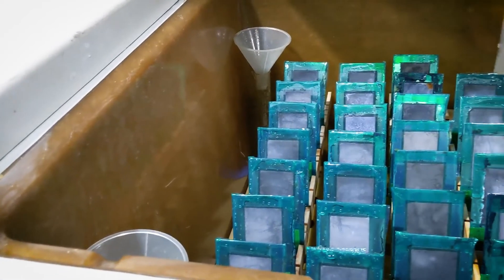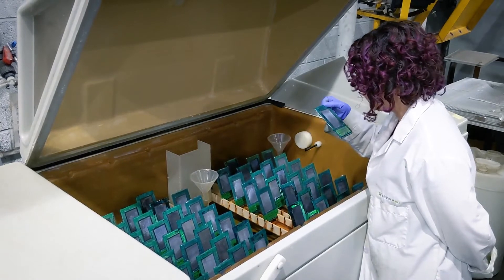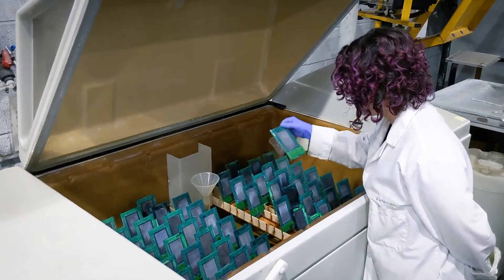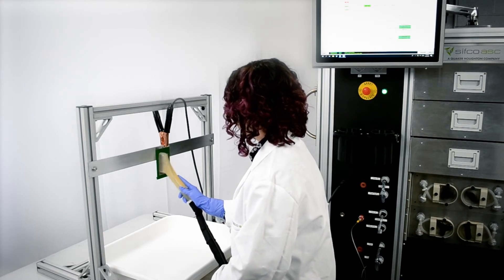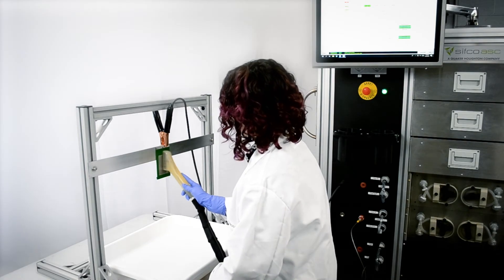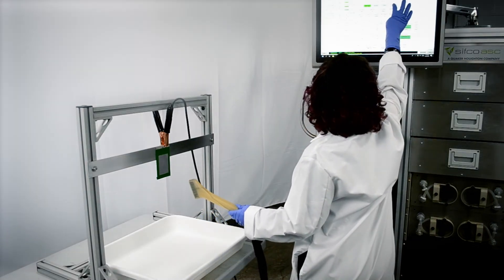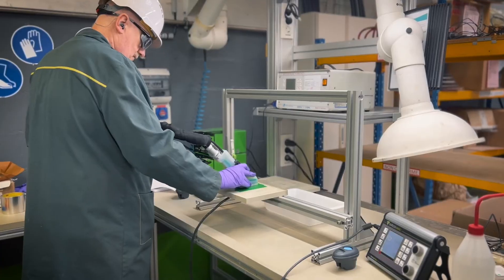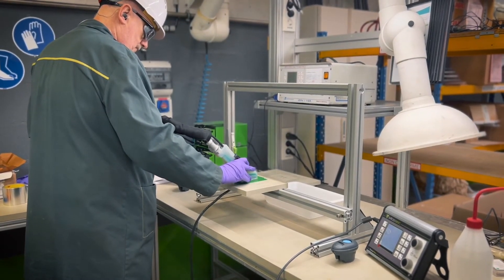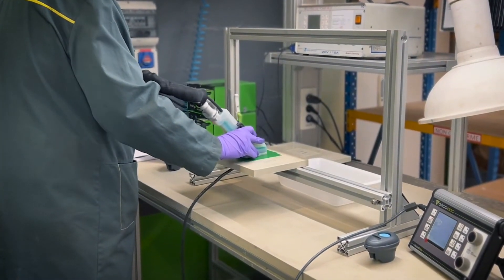With the Advanced Solution Control System, the applications are essentially endless. After hundreds of samples being put through our rigorous tests, we can confidently say that the repeatability and reproducibility of the deposits plated with the dripless tools are comparable, if not improved, over the standard brush plating processes. We've seen an improvement in the zinc nickel, where the as-plated thickness has exceeded the target thickness by 15%, while still maintaining the optimal nickel composition of 10–14%, ideal for providing corrosion protection. Our deposits are tested to the salt spray method ASTM-B117, and plating zinc nickel with the ASC dripless tooling, we've seen great results achieving 96 hours as well as 128 hours without visually showing white corrosion product, satisfying various industry specifications.